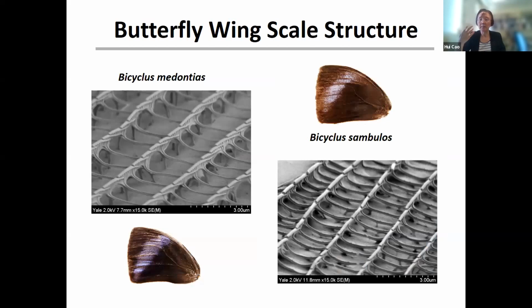So then, as I mentioned, there are two species that already evolved in nature to have this violet color. They actually generated it by the same method as we did in the lab. They also have similar structures, and this color is generated by thin film interference from the lower lamina, which turns out to be thicker than in the other species. Because for those two species the lower lamina is thicker, the thin film interference will make the reflection peak at a longer wavelength. That's why we can see the color.